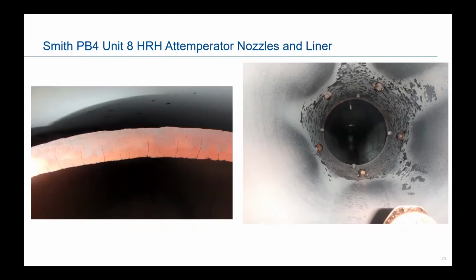And then here recently, last fall, we discovered what you can see in these photos. This is a hot reheat attemperator. The first photo to the left is the liner itself, at the edge of the liner furthest away from the attemperator, and you can see the cracks starting to develop there in the liner. Also, on the other unit at this particular site, there were cracks developing just downstream of the spray nozzles in the liner. Pretty severe cracking, where we're concerned about this liner starting to break apart.